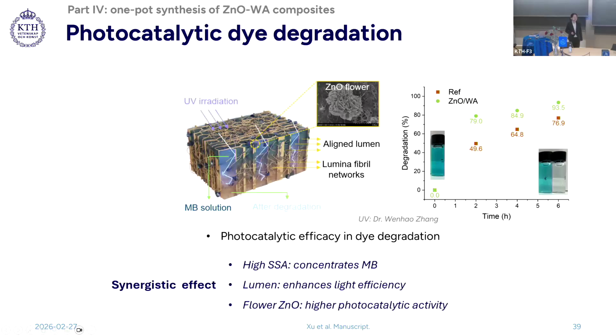This performance can be attributed to the synergistic effect between wood aerogel and the functionality of zinc oxide. The high specific surface area of wood aerogel concentrates methylene blue molecules close to zinc oxide. The lumen, which acts as aligned channels, enhances light efficiency by multiple light scattering. The flower-shaped zinc oxide was also reported to have higher catalytic activity due to its larger amount of oxygen vacancies.